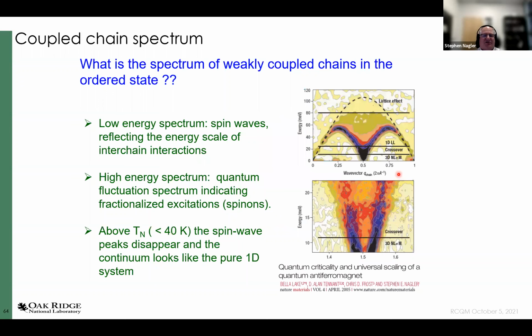And what we see is the following. If you're above the Néel temperature, which turns out to be 40 Kelvin for KCuF3, you see something that just looks exactly like the one-dimensional solution for non-zero temperature. If I'm below that temperature, if I look at very low energies that are characteristic of the interchain coupling, I actually do see sharp spin waves.